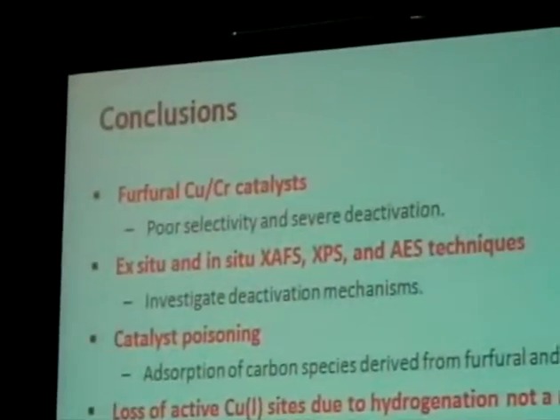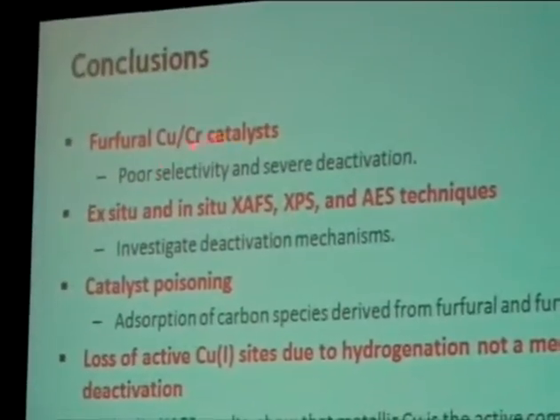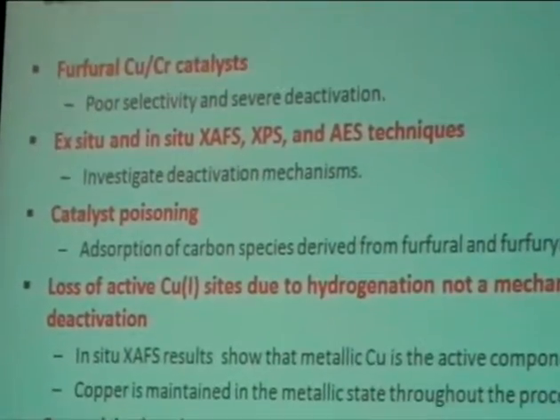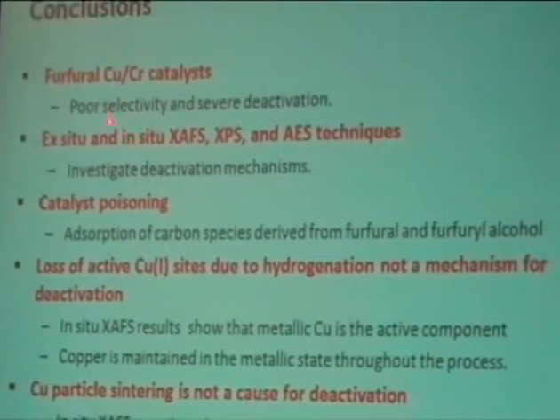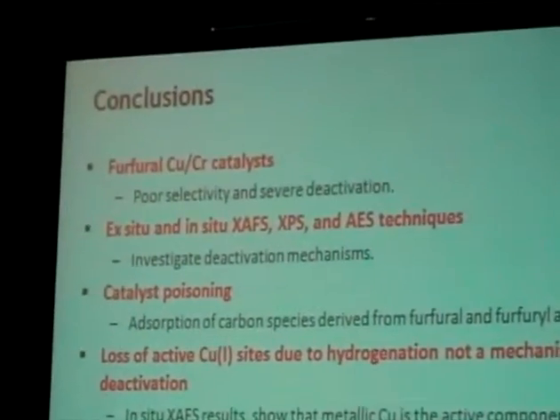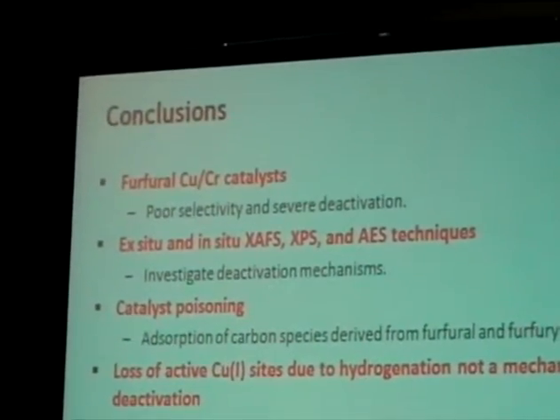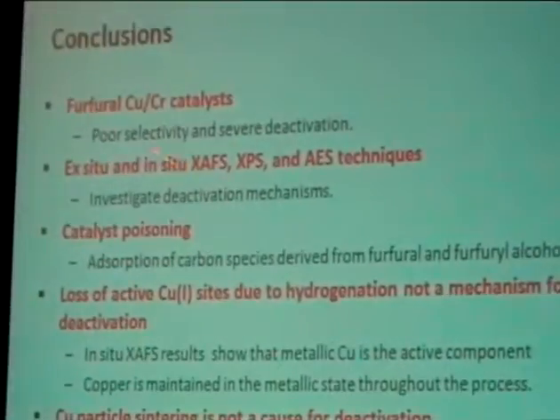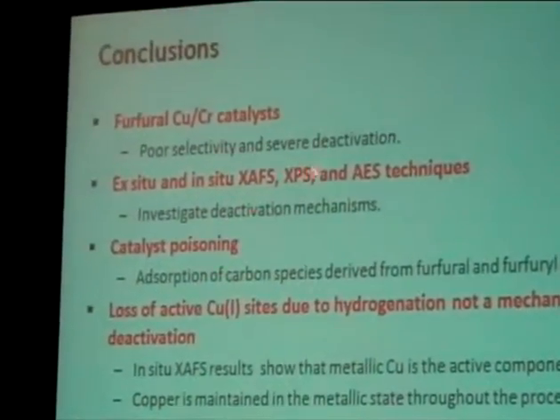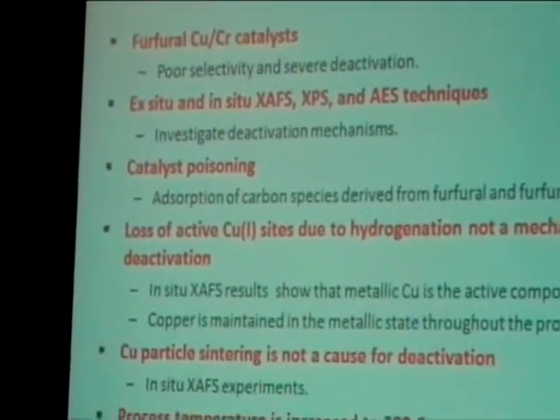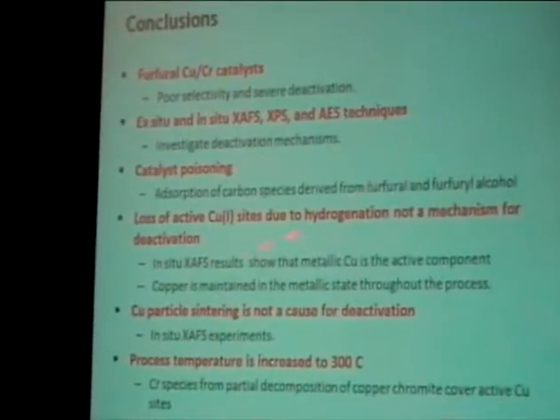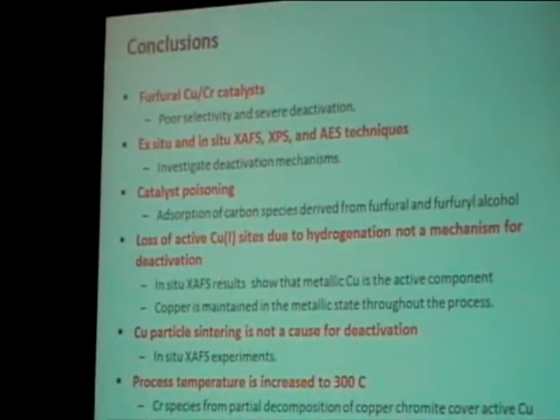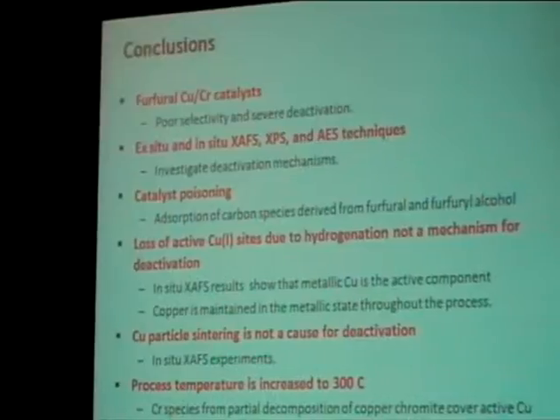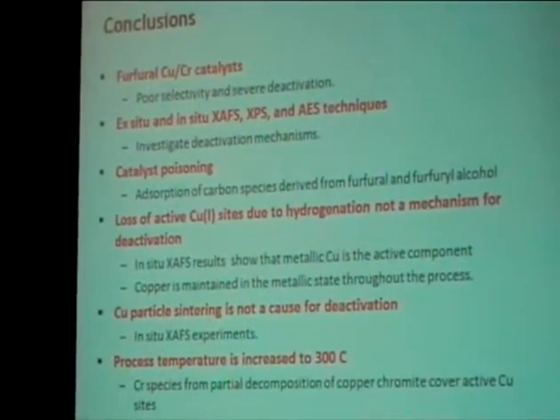In the case of these furfural copper chromite catalysts, the catalysts by themselves have relatively poor selectivity, and they do deactivate quite quickly. We've done both in situ and ex situ XAS, XPS, and Auger electron spectroscopy to investigate the mechanism. We find that the mechanism for the deactivation is twofold.